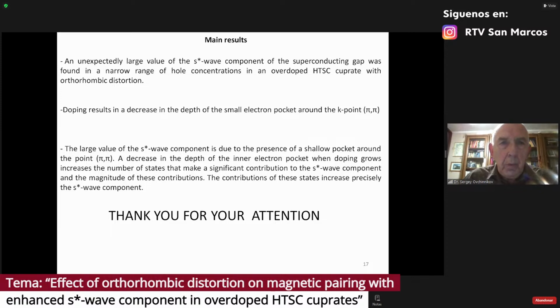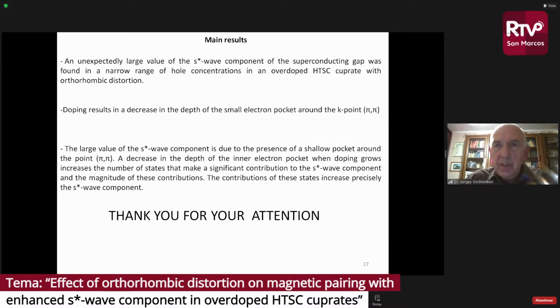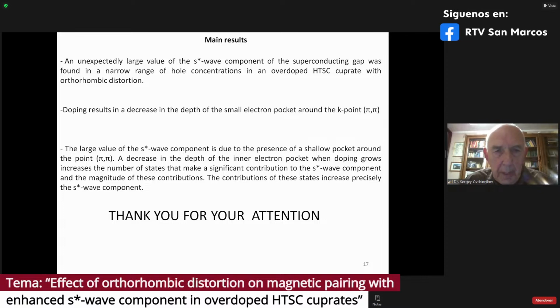What is the main result of our paper? We found an unexpectedly large value of the S-wave component in the superconducting gap in the narrow range of hole concentration in the overdoped high-Tc cuprate with orthorhombic distortion. Doping results in an decrease in the depth of the small electron pocket around the k-point (π,π). The large value of the S-wave component is due to the presence of the shallow pocket around the point pi with a small spectral weight.